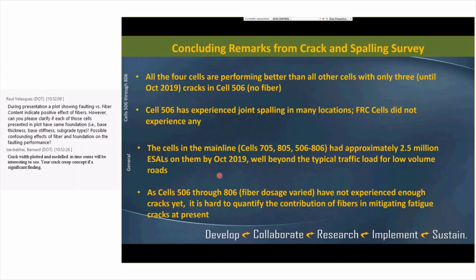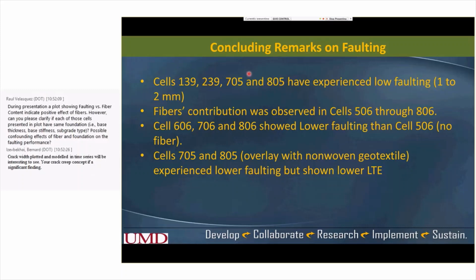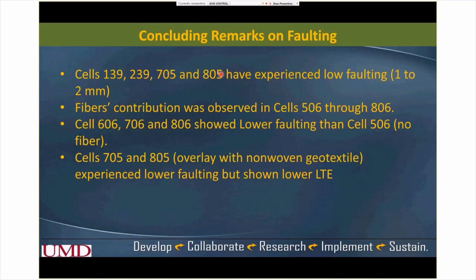Now on the faulting, as you saw, cells 139 and 239, even though they are damaged by fatigue, their faulting was less. And then the fibers' contribution was observed in 506 through 806. Cells 606, 706, and 806 showed lower faulting than cell 506 with no fiber. Cells 705 and 805, even though they showed really low LTE, had less faulting, probably because of the geotextile.